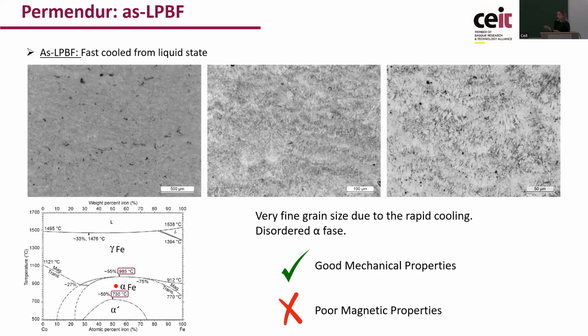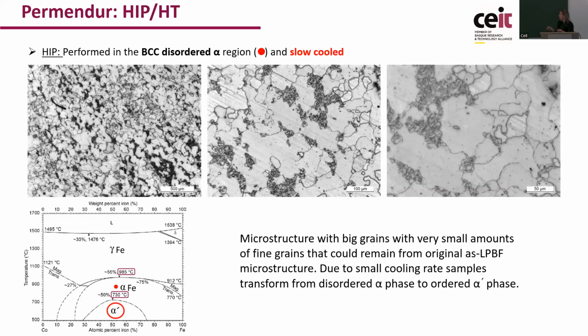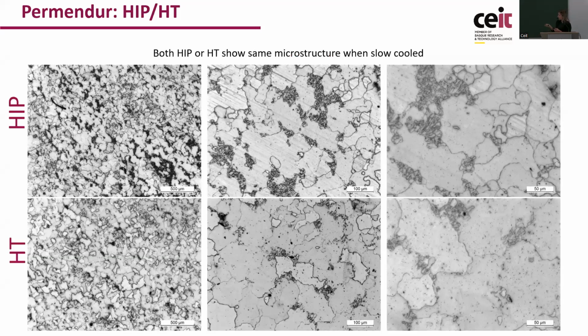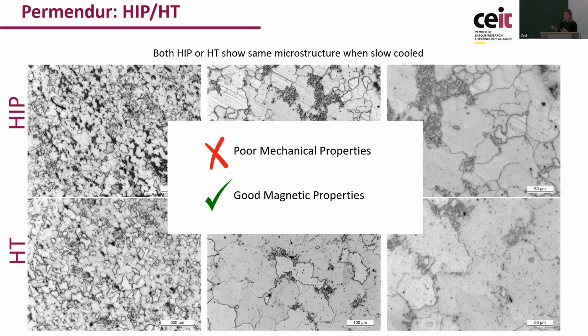So for that, the heat treatments are very useful. The standard heat treatment considers making a treatment at these temperatures with a holding time and then slowly cooling. When this happens, the microstructure changes completely. And in this case, we can observe that the grains are very big. And although there is still a little bit of small grain coming from the SLM material, most of the sample is based on these big grains that are related with the alpha prime order phase. So when changing from disorder to order, what we obtain is very good magnetic properties, which is what we were looking for, but on the contrary, we again lose the mechanical properties, and the material is very brittle and difficult to handle.